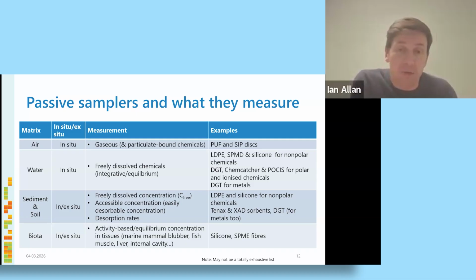LDPE and silicone are mainly used for looking at these non-polar chemicals, but there have also been groups working with Tenax and XAD sorbents or DGT in some cases. And with the DGT, with multiple deployments alongside, you can also look at desorption rates. And then the final matrix is biota. That's been done a little bit, mainly ex situ. It's activity-based equilibrium sampling in tissues. There have been applications to marine mammal blubber, to fish muscle, liver, and the internal cavity of fish. Basically it involves bringing the concentration of the chemical of interest in the polymer to equilibrium with the tissue of the organism that was sampled.